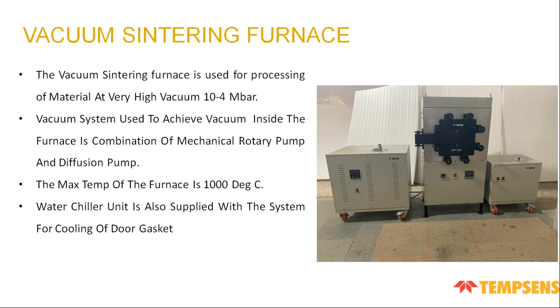This is basically a vacuum sintering furnace. When a sample is to be heat treated at high temperature with vacuum, this type of furnace has been designed. The vacuum sintering furnace is used for processing of material at very high vacuum, maybe around 10 to the minus 4 millibar, and the vacuum system is used to achieve the vacuum inside the furnace. The vacuum system comprises a mechanical rotary pump and diffusion pump, and the material is heated at 1000 degrees centigrade with continuous vacuum system. The maximum temperature is 1000 degrees centigrade, and a water chiller unit is also supplied with the system for cooling of the door gasket.